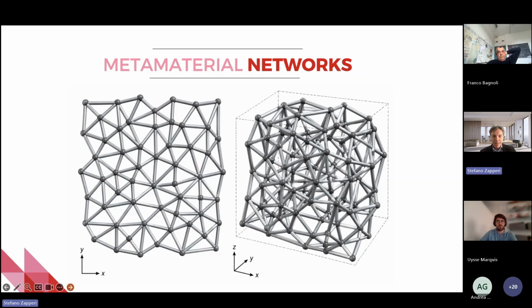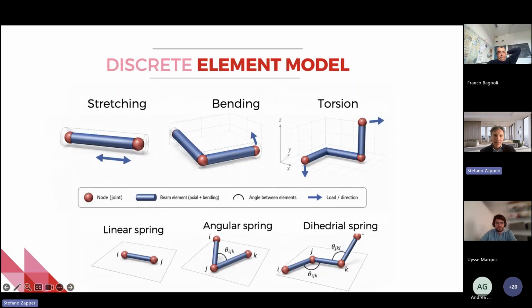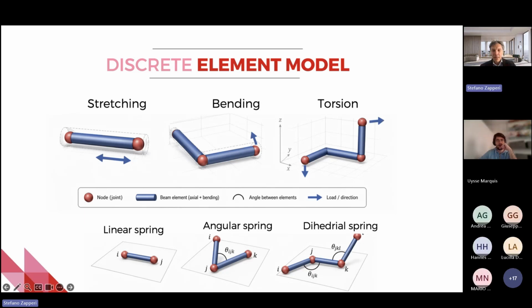And unfortunately, this is not just springs and balls, because that would miss most of the physics, but we have to take into account all the interactions. This can be done with a simple, physics-inspired discrete element model in which we have stretching. That would be your linear spring, as in most models that physicists use. But then, as polymer physicists do, we also want to have bending, the fact that we can flex the structure, and we simulate bending by adding angular springs. And then we also want to have torsion, and torsion we simulate by dihedral springs. So these are typical interaction terms that polymer physicists use, and we borrowed from them.